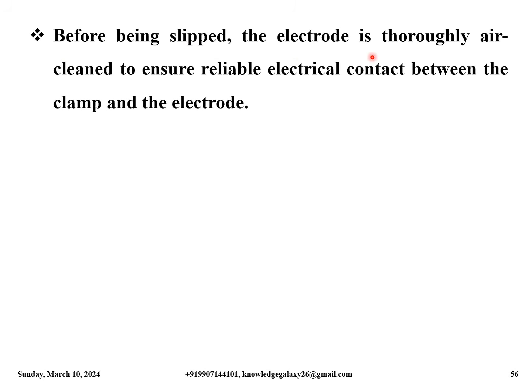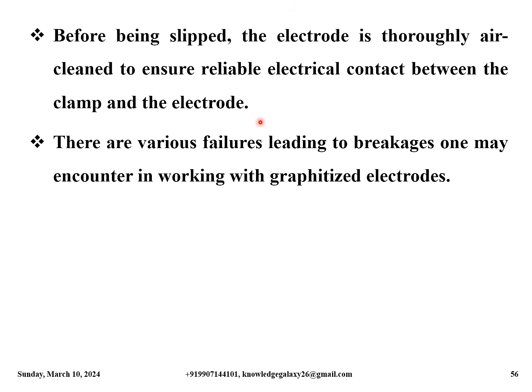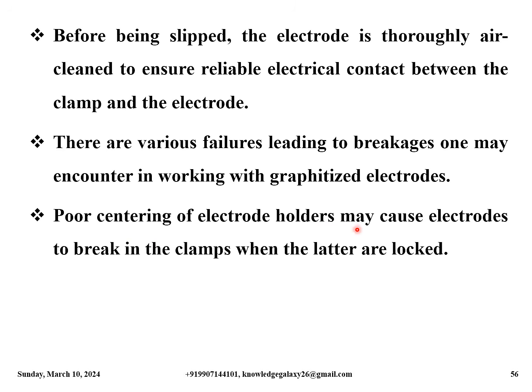Before being slipped, the electrode is thoroughly air cleaned to ensure reliable electrical contact between the clamp and the electrode. There are various failures leading to breakage one may encounter in working with graphitized electrodes. Poor centering of electrode holders may cause electrodes to break in the clamps when the latter are locked. Next, poor contact in the nipple joint is quickly discovered due to sparking and local incandescence. Poor contact may also lead to electrode breakage.